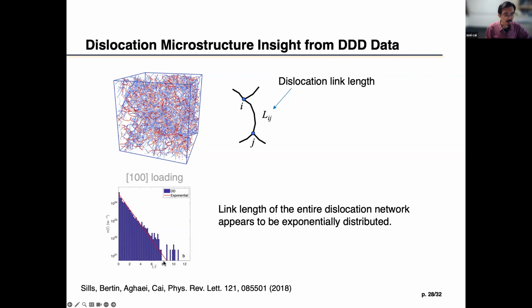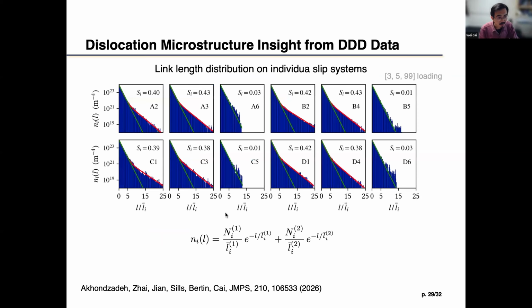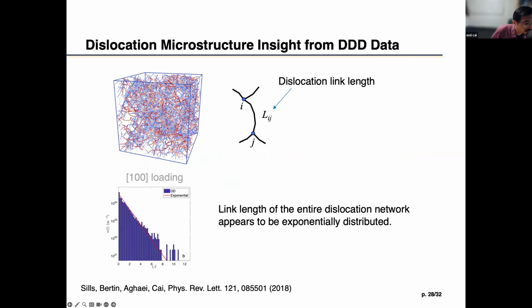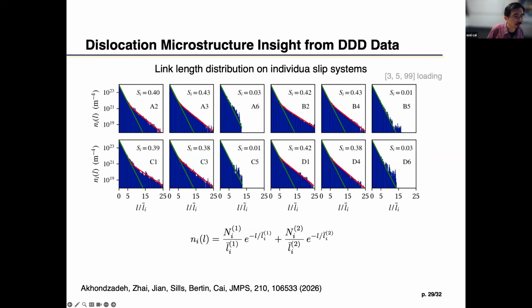That's kind of interesting, but that was an aggregated plot of the whole thing, and that's okay if you do a highly symmetric orientation loading because it's pretty isotropic. So more recently, we tried to extend the analysis to individual slip systems. There are 12 slip systems, and we look at it very carefully because this one expands 3 orders of magnitude, but we collect more statistics, so we go by about 6 orders of magnitude.